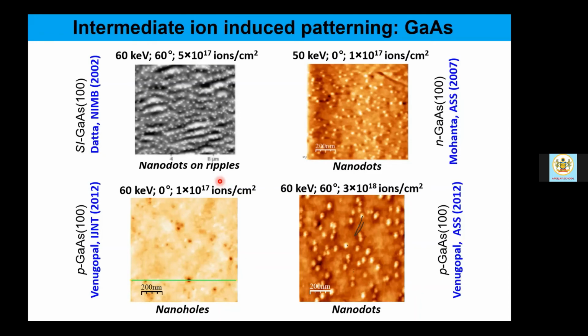But still, dot patterns, or in some cases, ripple patterns with clear signature of dot formation at the top of the surface are reported. But then they are very different surfaces as well. One is semi-insulating gallium arsenide, then N-type gallium arsenide. So N-type gallium arsenide and P-type gallium arsenide, mostly we get to see this dot formation as is seen from these two top and bottom frames. One was 50 keV, another is 60 keV, not much different. And 60 keV for P-type gallium arsenide also, we got to see this nano hole pattern at 0 degrees.